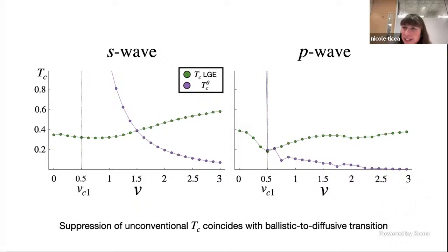Which aspect of this story? Like the fact that disorder would hurt an unconventional superconductor, if we go by this statement. Right? Well, I'm not sure what you're about to say, but my understanding is that Anderson's theorem only applies to the weak coupling instability. From a Landau-Ginzburg perspective, there's a transition temperature when the product of V times the static pairing susceptibility is of order 1, which doesn't really care about the behavior of the logarithmic divergence as T goes to 0.